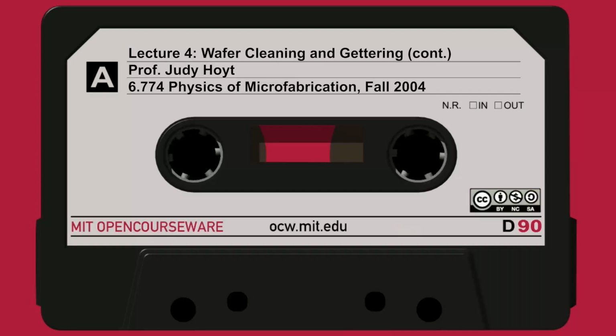And what we define as this segregation coefficient, just as we did before in liquid-solid segregation, K0, is the ratio of the concentration of the total gold in the wafer divided by that that's in the silicon. So that's our segregation coefficient. And we can just simply plug in these exponentials and ratio them as shown in the equation. So if EA1, the activation energy A1, minus EA2 is a positive quantity, then K0 is going to decrease as temperature increases. This tells us something about where the metal wants to reside.